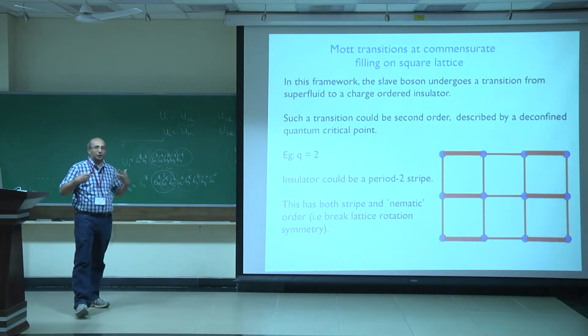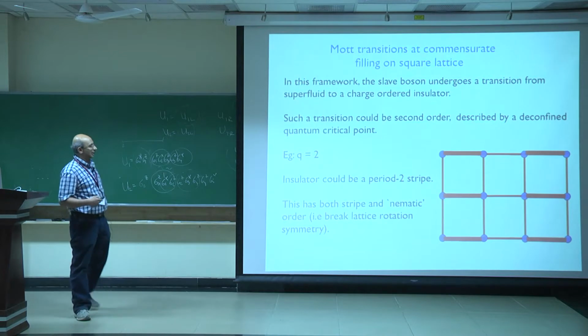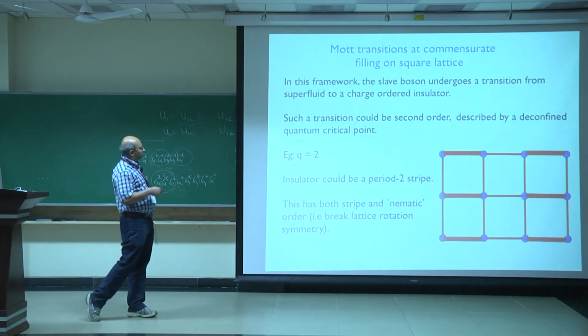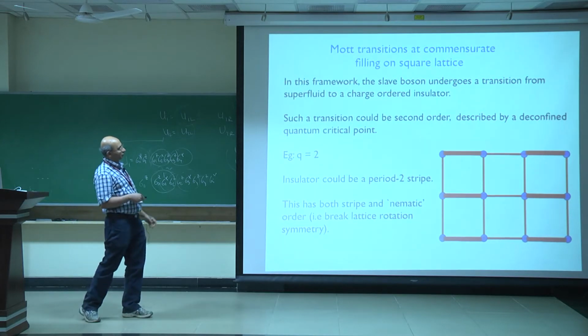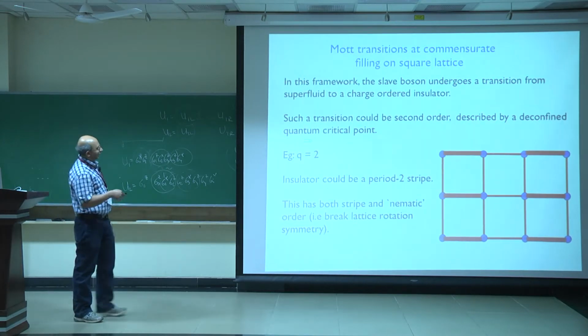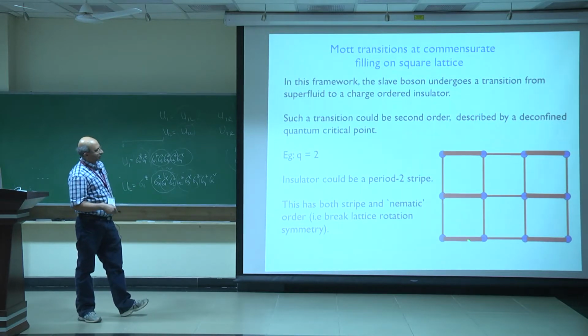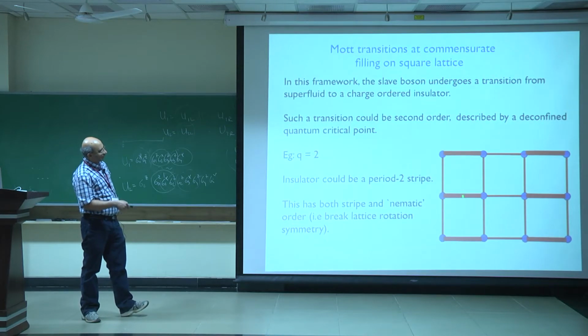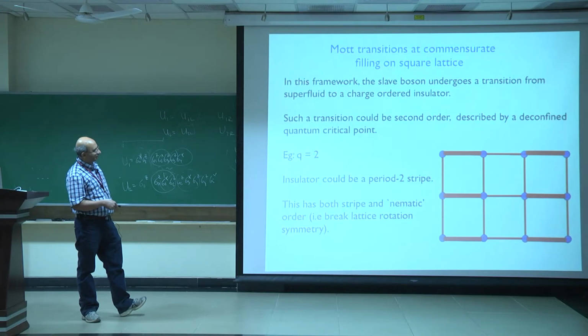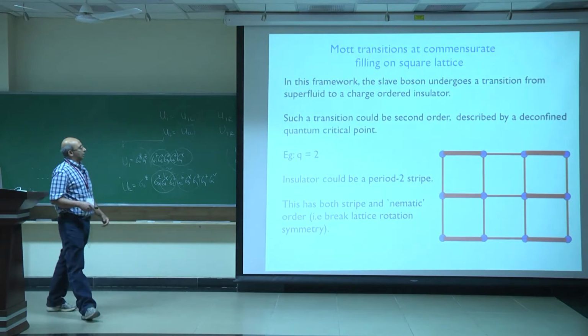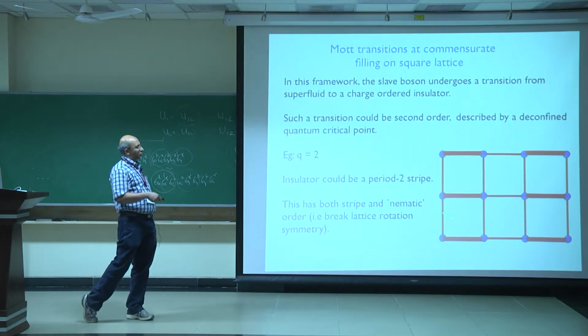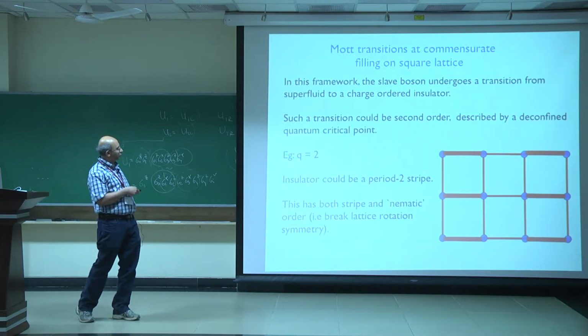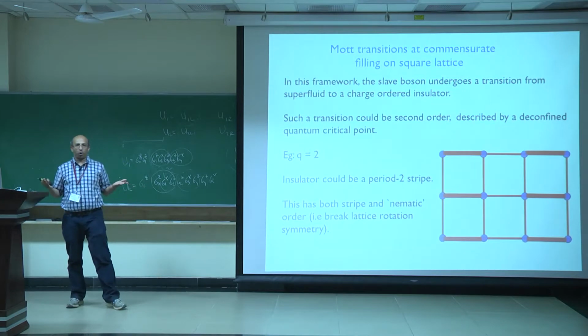No, in the sense that it's a fluctuation-driven effect. It's a mean field level. It's second order. Okay? So to illustrate the point, I'm anyway not interested in q equals 2. I'm interested in q equals 4 or q equals 5. At q equals 2, one insulator that you could get is a period 2 stripe, where the bosons sit at the bond centers. It's a so-called bond-centered stripe. It breaks both lattice translation symmetry and lattice rotation symmetry. It has both stripe order, translation breaking, and rotation breaking, so-called nematic order. Now we know that the superfluid to Mott insulator transition at q equals 2 is a complicated problem, right?